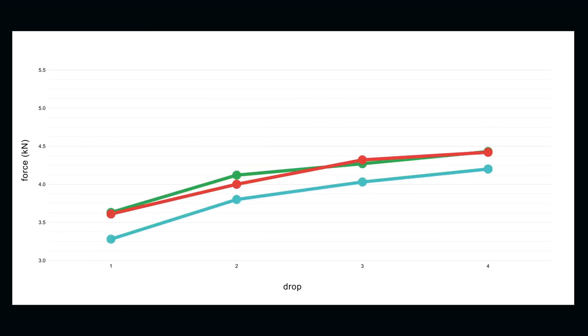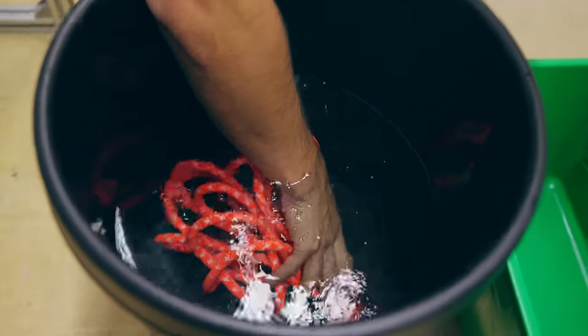Here are the results. If we average all the dry samples, we get a baseline showing how force increases with every fall, which shows that the rope doesn't have enough time to fully recover between drops. So let's see what happens when the ropes are wet.